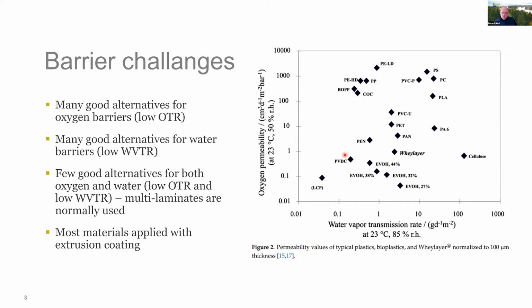As I said, the reason you use this complicated structure is that, when it comes to polymeric materials, you have a good oxygen barrier like cellulose, which has a quite low oxygen permeability, whereas the water vapor transmission rate is quite high, which means it's a poor water barrier. Or if we take polyethylene, you have a very low water vapor transmission rate but quite high oxygen permeability. So you have a good water barrier but a bad oxygen barrier. You have quite a lot of materials in between, but finding materials that have both low oxygen permeability and low water vapor transmission rate is a little bit harder.